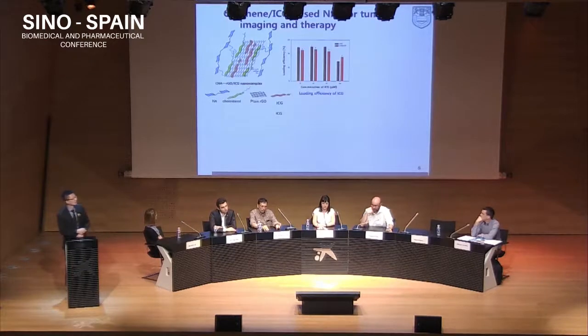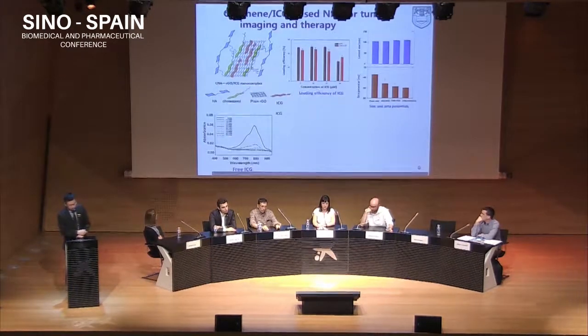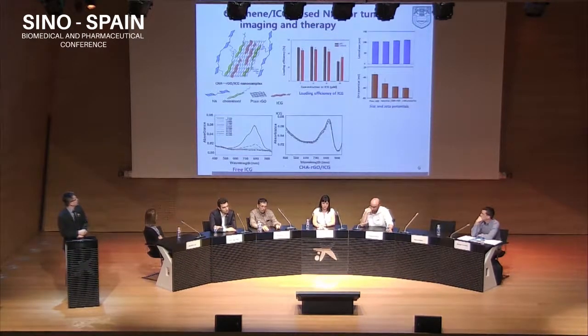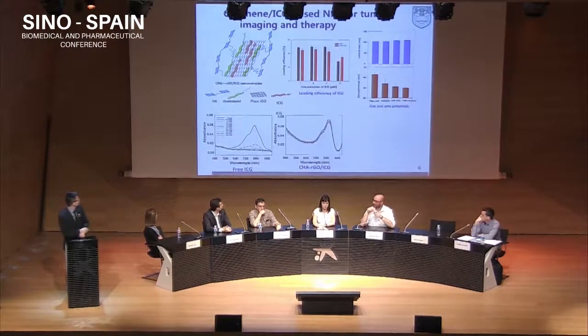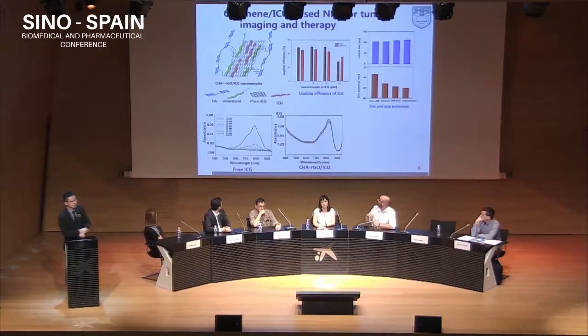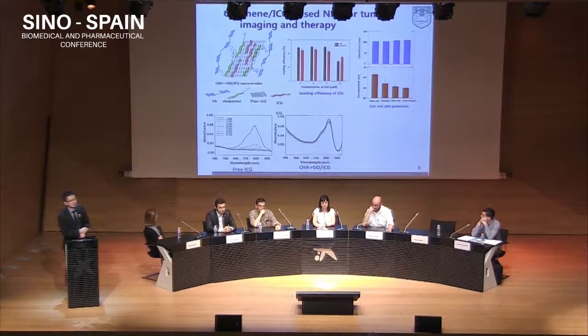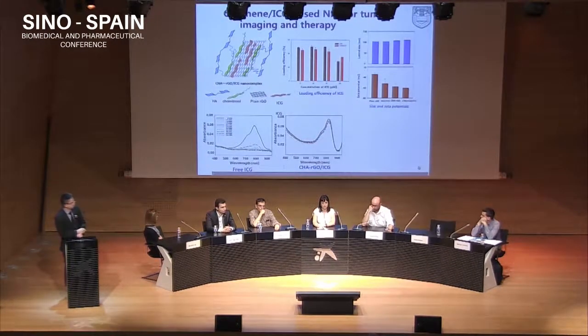Due to the large surface area that is an intrinsic property of graphene, I use graphene here as a carrier for the ICG. The system I call CHA-rGO, meaning the surface of graphene is modified by hyaluronic acid for active targeting. We optimized the loading efficiency of ICG onto the CHA-RGO and measured the size and the potential of the particles.